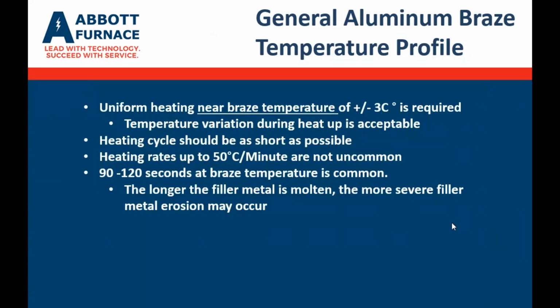But this is a very typical temperature profile for aluminum brazing. The plus or minus 3 degrees C at braze temperature is required. There can be some temperature variation during the heat up cycle, and that is acceptable as long as the parts all come together at brazing temperature within that temperature window.